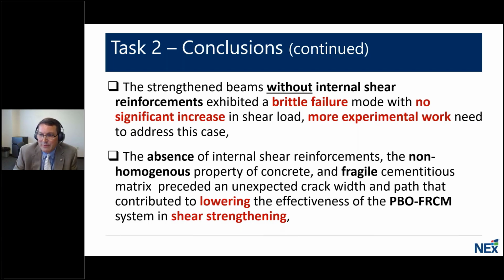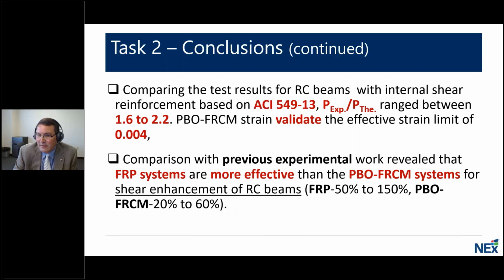The absence of internal shear reinforcement, the non-homogeneous property of the concrete, and the fragile cementitious matrix produced an unexpected crack width and pattern that contributed to lowering the effectiveness of the PBO FRCM system in shear strengthening. And then finally, relative to the code, we saw that there was a 1.6 to 2.2 conservative nature in terms of what's predicted versus what we found experimentally. And also the PBO FRCM strain validated the effective strain limit of 0.004 at failure. And then comparing with previous experimental work, this revealed that FRP systems are more effective than the PBO FRCM systems for shear enhancement of reinforced concrete beams.